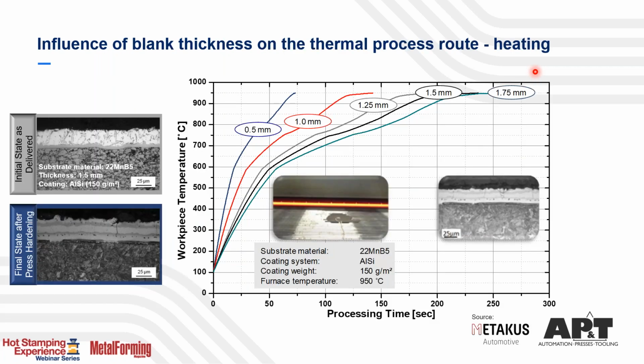So what are the influencing parameters when walking through that press hardening process? First of all, we have the heat treatment process, heating up the material. I brought an example here of a 22MnB5 with an aluminum silicon coating, 150 grams per square meter in different thicknesses. So what you see in this chart are different blank thicknesses. And what you can clearly see is that every single blank thickness behaves differently when heating the material up. Quite rapidly for low gauges and longer heating time or ramp up time until you reach full austenitization for thicker material.